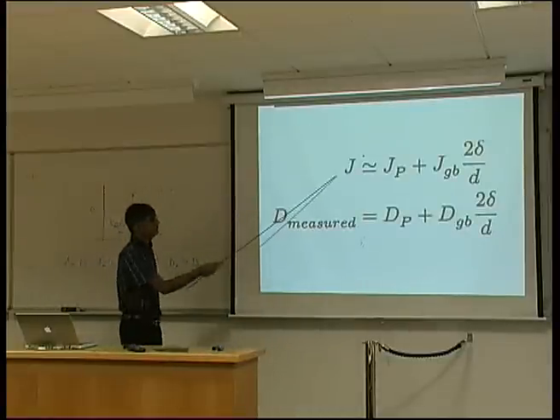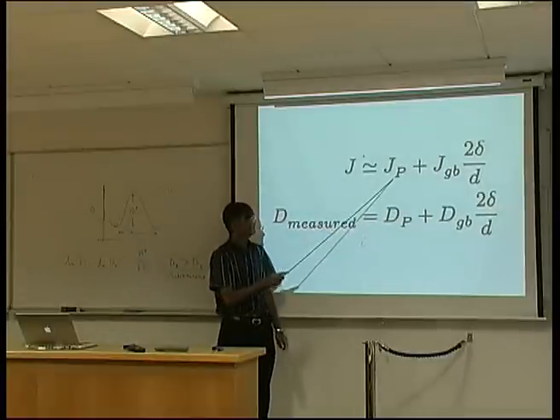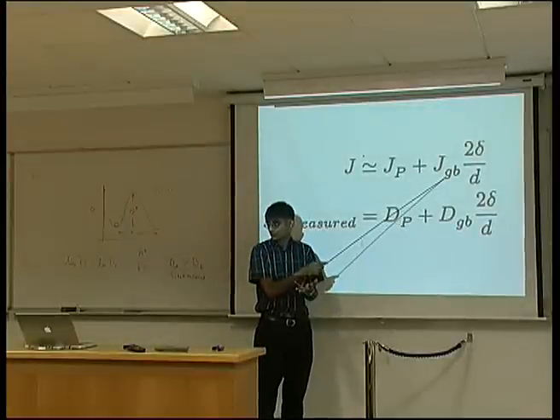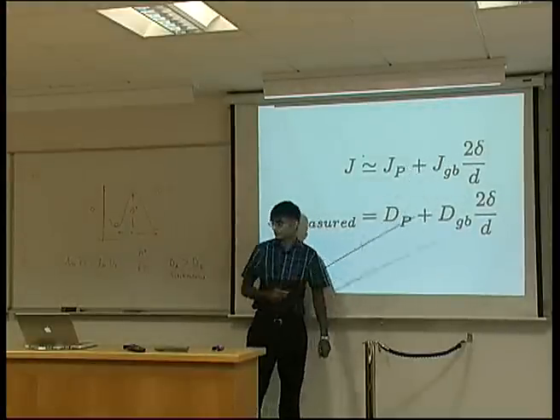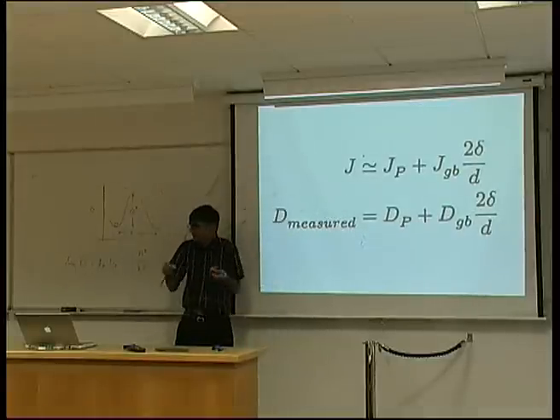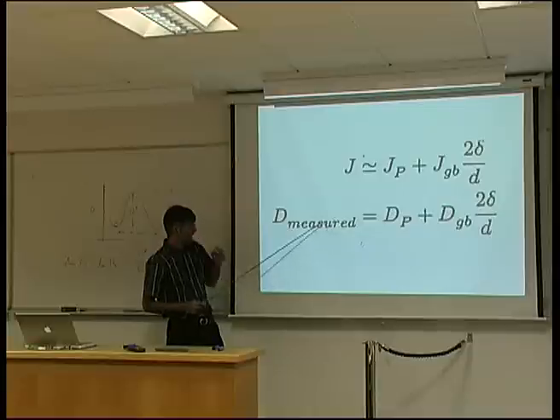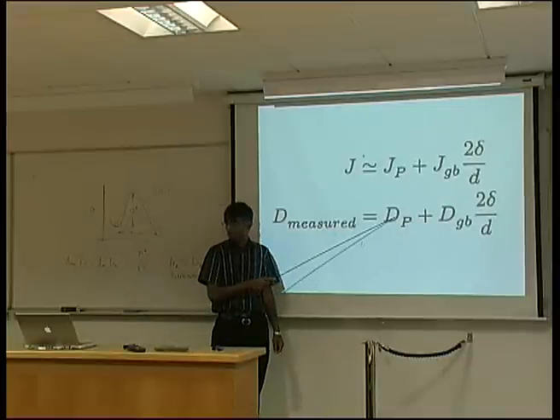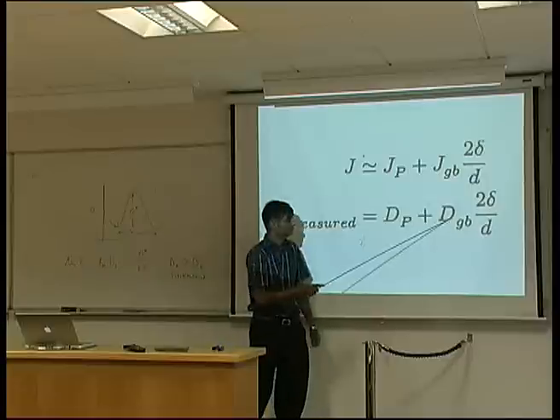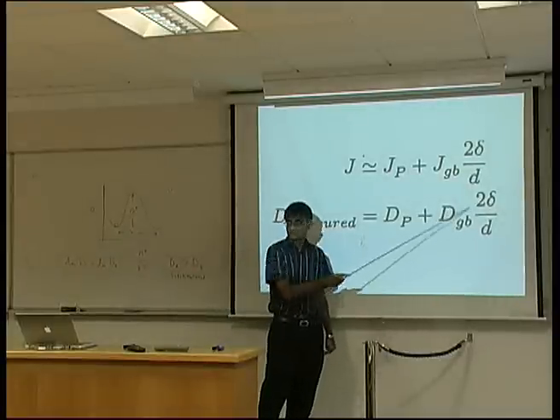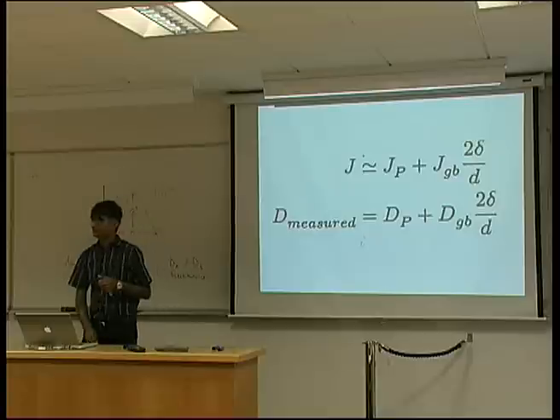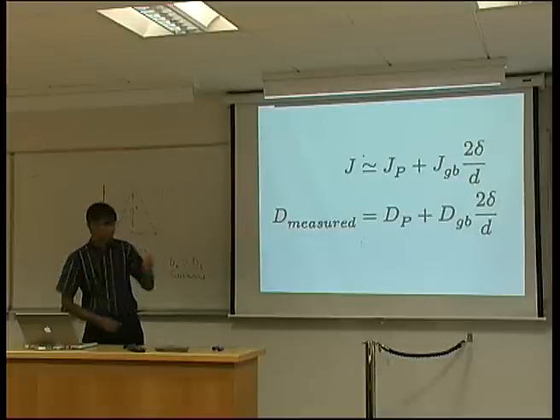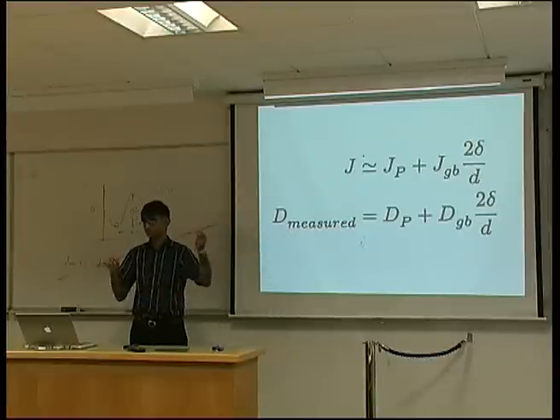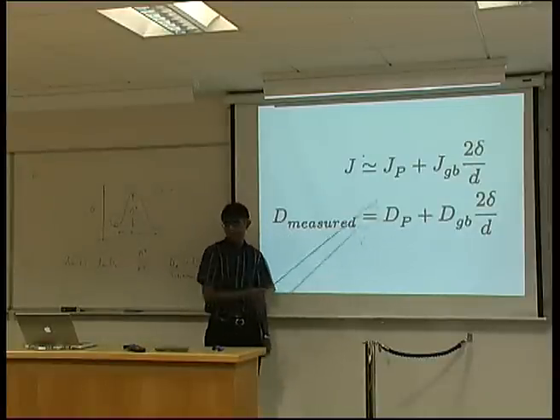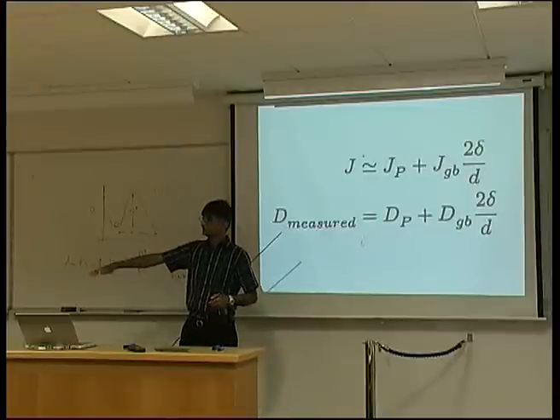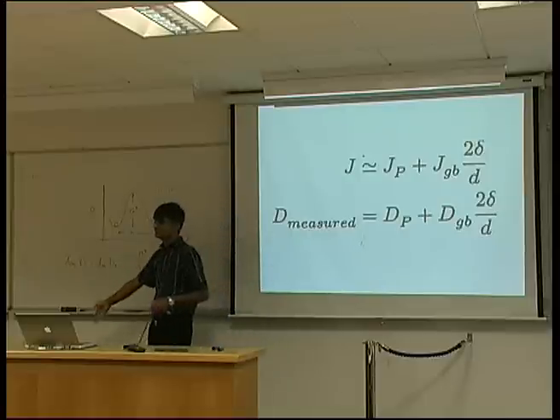So the total flux will be the flux through the perfect material plus the flux through that grain boundary, that defective region, which scales with the fraction of that defective region. And this is nearly one because the boundary is a very thin region of material. So your measured diffusion coefficient will be a function of diffusion through the perfect lattice plus diffusion through the grain boundary, which scales with the fraction of grain boundary you have in your material. Now when you plot the log of this diffusion coefficient versus 1 upon T, it won't be a straight line, because these are two different functions of temperature. So it will in fact be a curve, depending on which process dominates. Okay?